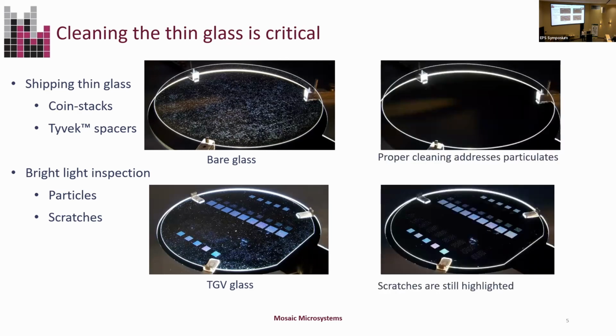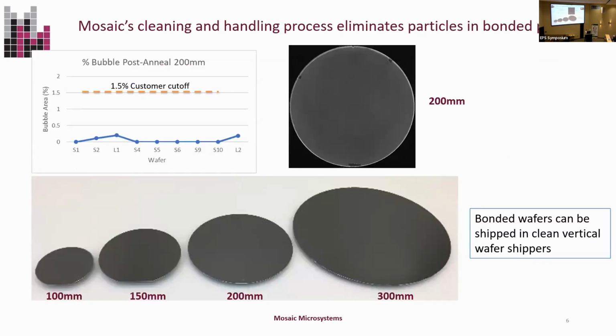So once we're done with it, though, we actually can see that the glass is really clean, and it's required for our very thin bond. It's required that it be particle free. We don't actually manage to clean the scratches; those stay, but we are particle free. And what that allows us to do is have a very